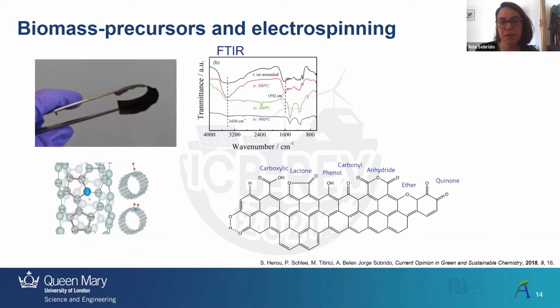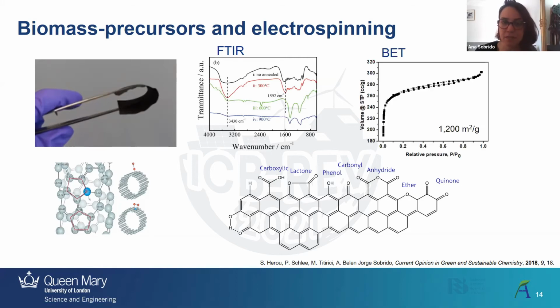And then the surface of these lignin fibers is populated with a lot of functional groups, mostly oxygen, which is going to be beneficial particularly for one of the applications I'm going to show later, which is redox flow batteries. And then they're highly porous, and again, this can also be tuned depending on the amount of polymer and the different modifications that you do to the fibers. So that's the characteristics and features of the fibers that we can produce.